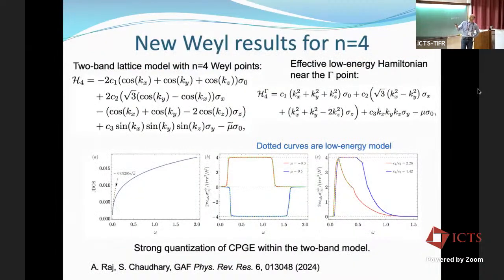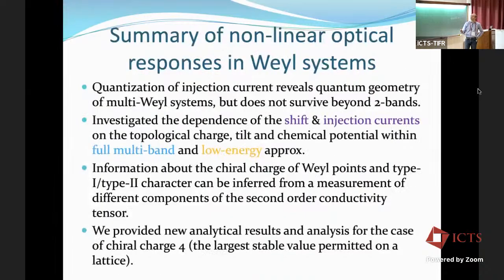So we also have results for n equals 4 that I won't spend too much time on in the interest of the other things. But we have exact results here. This is new for the literature. And again, if it's just charge 4 for a two-band model, you get perfect quantization. So that perfect quantization is an artifact of having two bands, and it's independent of the topological charge at that Weyl point. So, summary here: the quantization of injection current reveals the quantum geometry, but that quantization does not survive beyond the two bands.